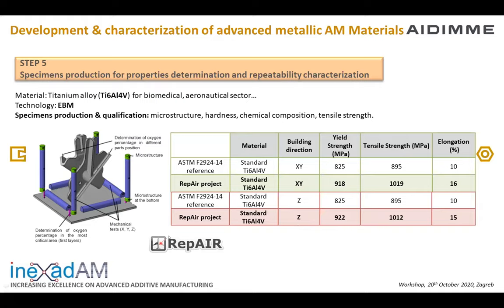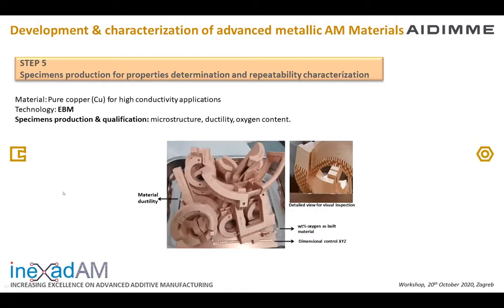After producing it, we saw the results comparing with the reference, with the standard for this material. So we saw that in both directions, the mechanical behavior was superior to the established in the reference. So this is a way to control and to qualify the process and this technology.